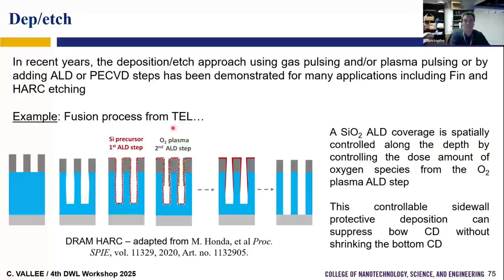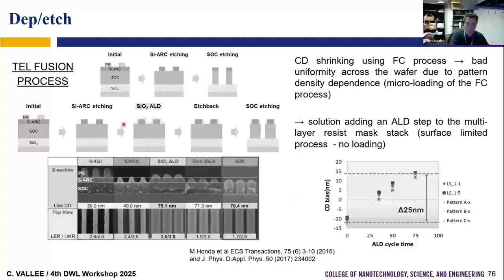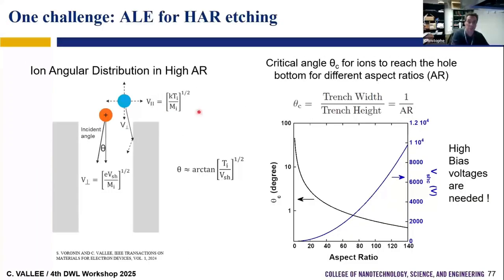So this example was proposed by Tokyo Electron, what they call the fusion process, where some ALD deposition steps are introduced inside the plasma etching process. And this is the same example to see the improvement regarding the CD bias when they add some ALD step inside the plasma etching process. So this is combining deposition and etch, and we are combining more and more deposition in etch process and etch process in deposition process.